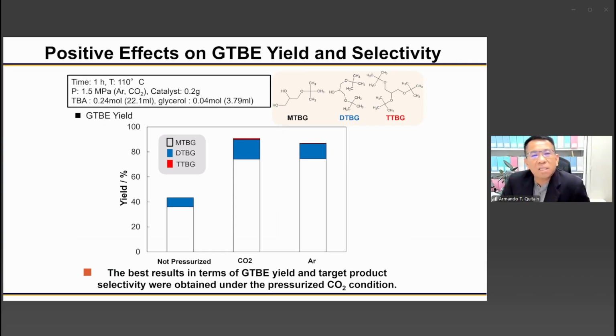And this is just a preliminary result. We are getting, I should say, positive result on pressurizing the system with carbon dioxide. Again, the addition of carbon dioxide will push isobutene to the surface of the catalyst for further reaction. And carbon dioxide will also react with water in order to produce carbonic acid, which will add up to the acidity on the surface of the catalyst.